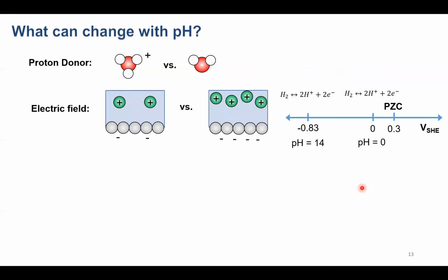And so we know that we also change the electric field across the surface. So how does this work? If we look at the figure on the right here, I'm showing the electrochemical potential scale versus what's called the standard hydrogen electrode, which is given a potential of 0 when the free energy of hydrogen gas is in equilibrium with the free energy of protons at 1 molar concentration of protons, so a pH of 0. If we now look at this same reaction, but at pH 14, we've decreased the concentration of protons by 14 orders of magnitude.